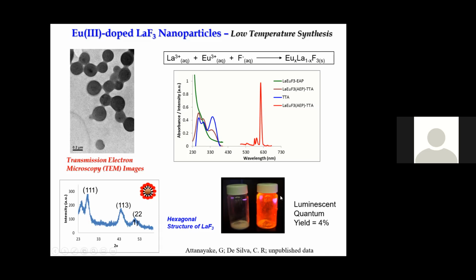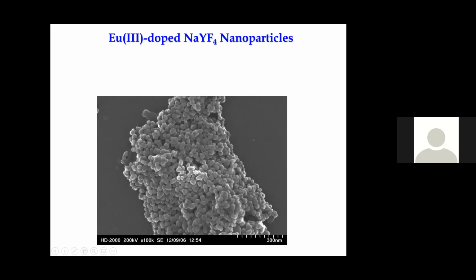So the student who did this work got 4%. So the particles are quite big. So what she wanted to do was make smaller particles and see whether we can enhance this efficiency, because in the Förster energy transfer mechanism, the energy transfer depends on the distance from the nanoparticle surface to the molecules. So she made some other types of nanoparticles using a high temperature method. She made some organometallic precursors and heated them to a higher temperature. You got the nanoparticles, and indeed they were small. These particles were like 20 nanometers in size.